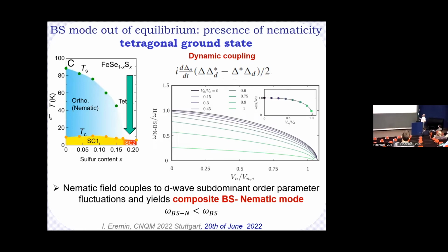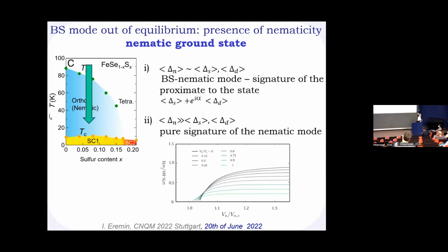We basically yield a hybrid Bardasis-Schrieffer nematic mode, or composite Bardasis-Schrieffer nematic mode. And actually, it further boosts the position of this mode to energies which are well below the initial Bardasis-Schrieffer mode that you expect. But what is more interesting is now to look into the situation when you are moving towards a state which corresponds more to pure iron selenium. And this is also very nice because this material can be grown as a large single crystal, and you can do all the nice measurements.